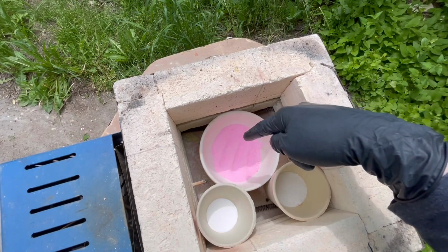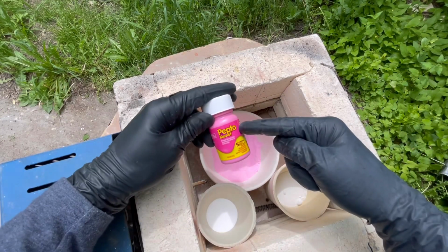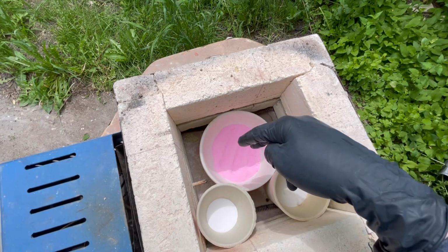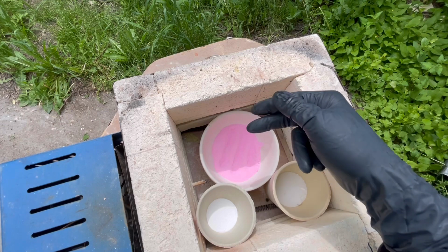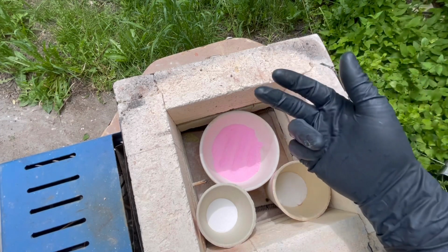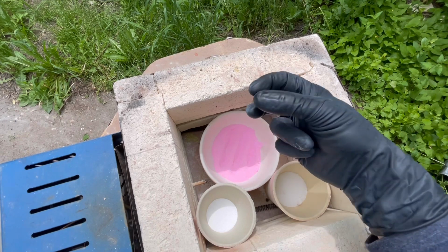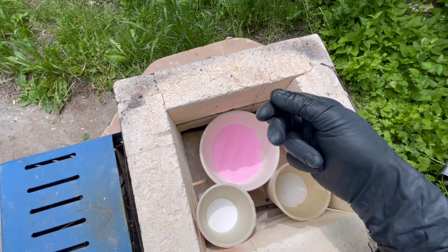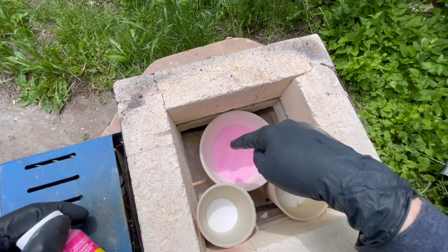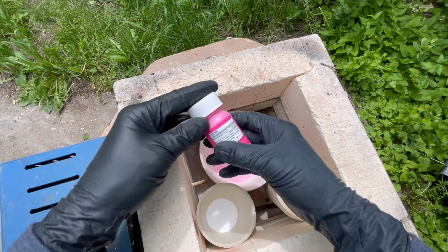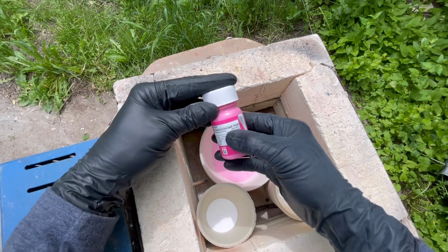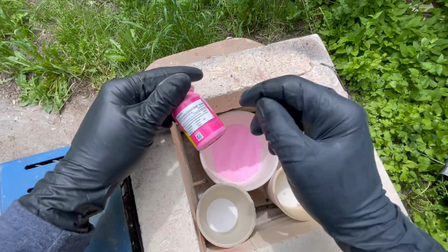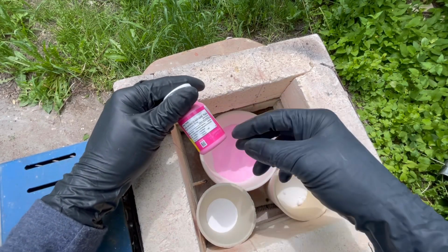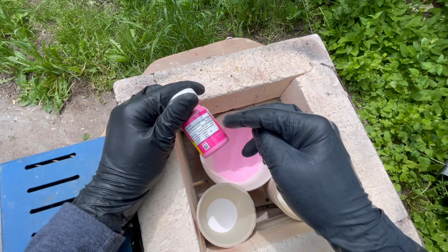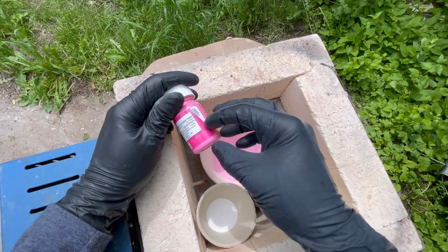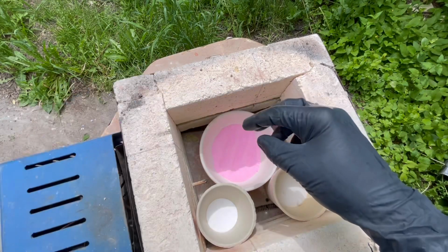Now you might have noticed this pink stuff here. This is 60 ground up Pepto-Bismol pills, and that is approximately 15 grams worth of bismuth. That is going to be used as the collector for pulling those precious metal particles together and bringing them down to the bottom of my container. Now, the reason I'm cooking this here is, first of all, to remove volatiles again, but also the bismuth subsalicylate, I hope I say that right, contains a lot of carbon. This stuff also has a lot of starch and other binders which contain carbon as well. Now, we do need some carbon to react with the bismuth to reduce it to metallic form, but the amount that's in here is just too much.